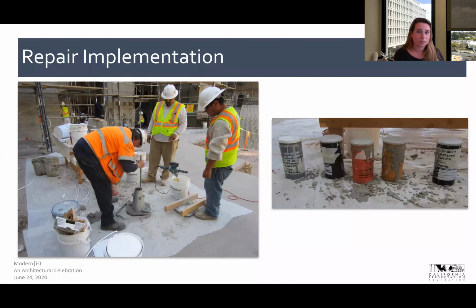Quality control with any concrete repair project is really important, making sure the material is as expected, that the material is consistent, that there aren't changes in constituents. And so that includes both plastic testing. On the left, you can see a slump test being done. So both fresh concrete testing during placement and during construction, as well as looking at hardened concrete properties, including compressive strength. That's where you see on the right-hand side, cylinders that were cast with concrete that will later be tested in a laboratory to monitor compressive strength and make sure that there aren't changes in constituents causing fluctuations in the compressive strength, either high or low. Both could be potentially problematic, but it's maintaining consistency and that the concrete is as expected and as was developed during the trials and the mock-ups.